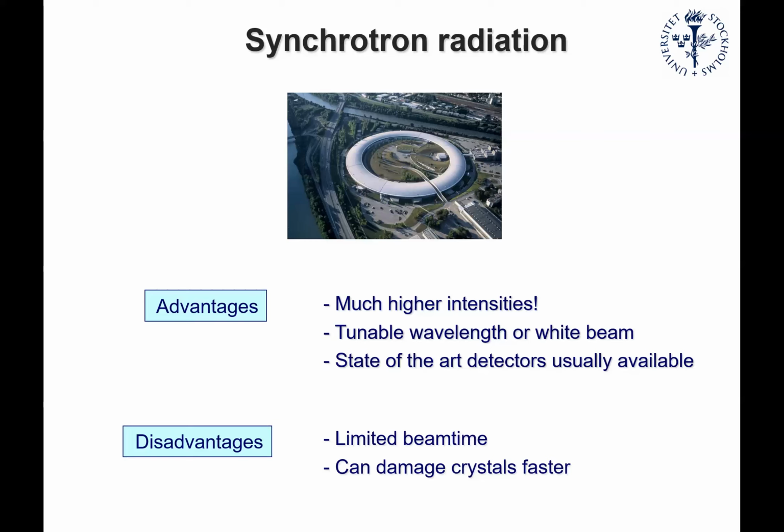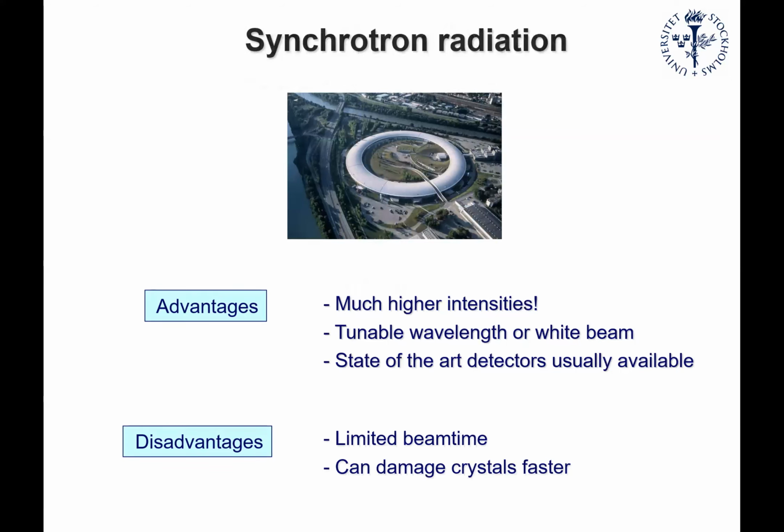Also, with a much higher intensity of the X-ray beam, you can also damage crystals a lot faster. So beam damage becomes much more problematic compared to, say, an in-house source. So yeah, if you go to a synchrotron facility, be careful if your crystal is being destroyed by the X-ray beam.